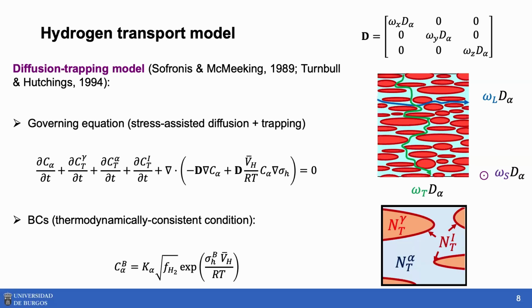Two main modifications: we don't use a scalar diffusivity, we use a diffusivity tensor, and the components of this tensor are related to the diffusivity through the ferrite and also to the tortuosity of the path. For example, in the longitudinal direction, which is the rolling direction, we expect elongated austenite grains, so the diffusion path for the hydrogen will be more straight. So the omega for the longitudinal direction, this tortuosity factor, will be closer to 1 because we are close to a straight path. And we are considering 3 trapping sites: hydrogen retained at the austenite phase, at the interfaces, or at other general defects within the ferrite phase.